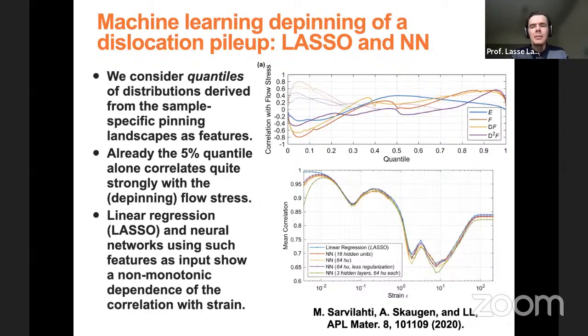Right. So now, again, we have to say something about the features that we use. Here, what we ended up using, because we need some kind of descriptor of the pinning energy landscape, of the pinning force landscape, is that we consider quantiles of distributions derived from the sample-specific pinning landscapes as features. And then we can also look at the correlation with the flow stress, which is the stress at which you start an infinite avalanche. So this is the critical stress, call it the flow stress, because then the system starts to flow indefinitely.